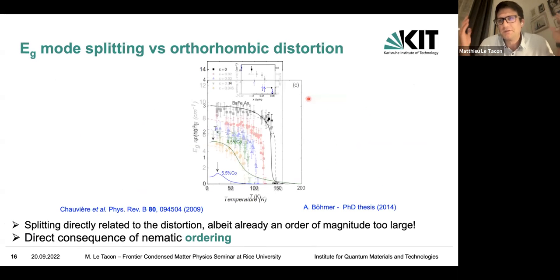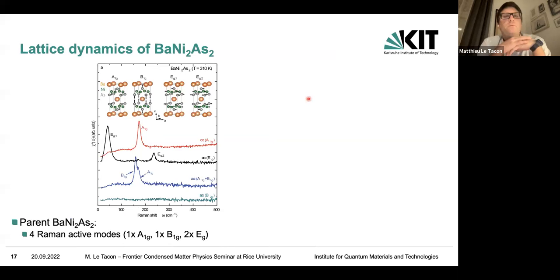Simply because you see the distortion in another manner, so it was just not so. It's a kind of side effect. Nevertheless, we tried to do that on BaNi2As2, and so we looked at the phonon spectrum. So we measured the Raman spectrum, and we found the 4 Raman active phonons.